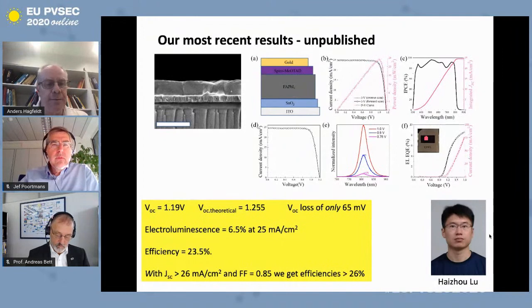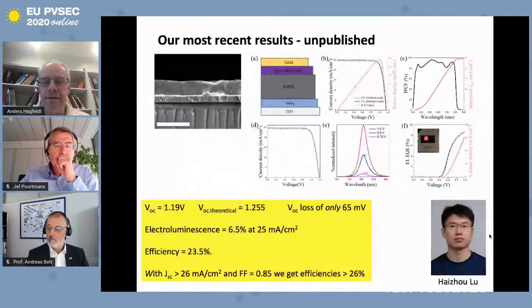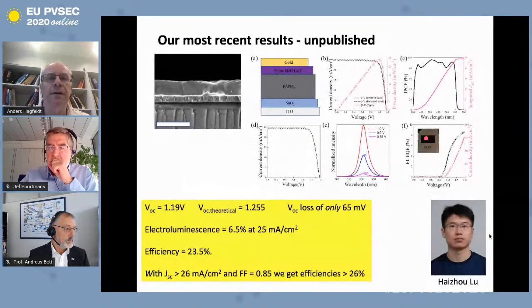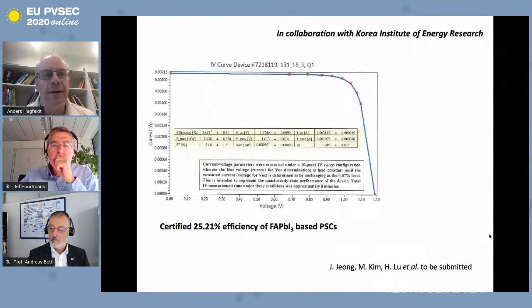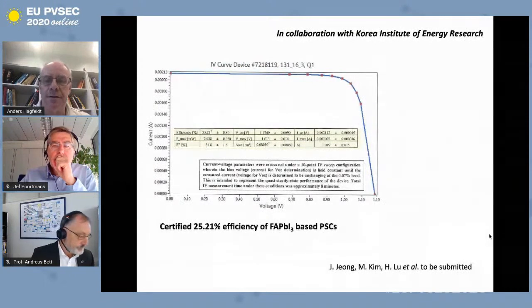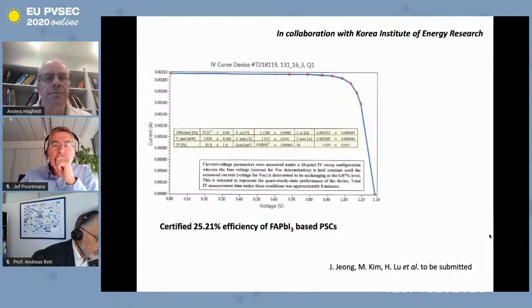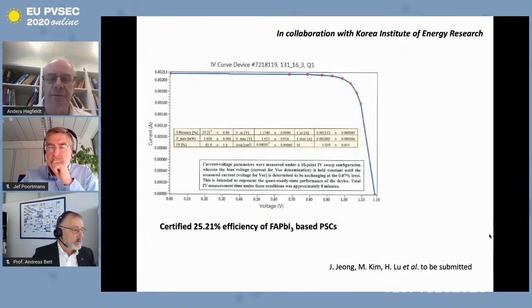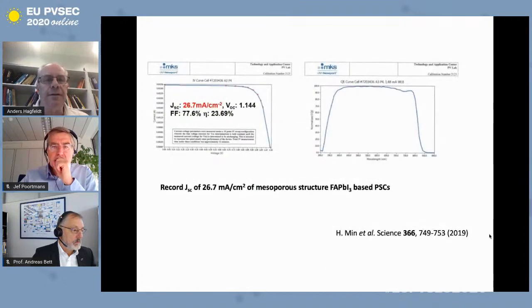So if we extrapolate a little bit and say that with this kind of band gap, it should be possible to have 26 milliamps. It's on the current, we are losing a little bit. A high fill factor of 0.85, that's a big challenge, but in principle possible. We think that it will be very possible to reach 26% and a little bit higher. And we are on the way here. We have also to be published a certified record together with the Korea Institute of Energy Research. It's our postdoc Jae-Ki Jeong and Haizhou Lu who's working with it at EPFL. And we certified recently 25.2% on this kind of FA lead I3 systems. So also on the current, there is a report in Science last year from Min et al., where they do reach higher than 26 milliamps per square centimeter.